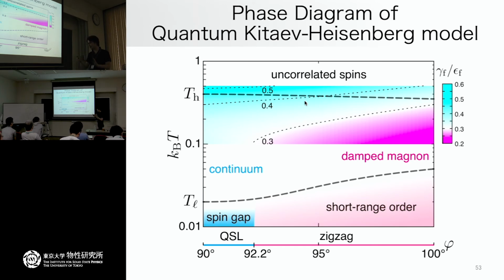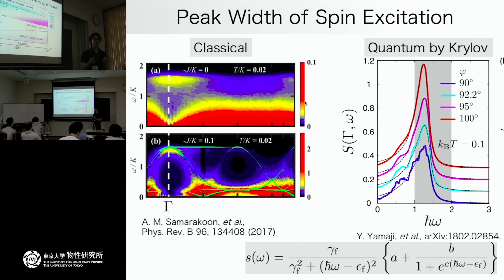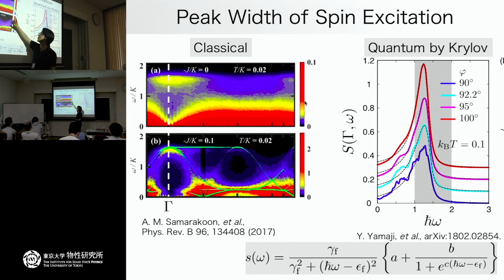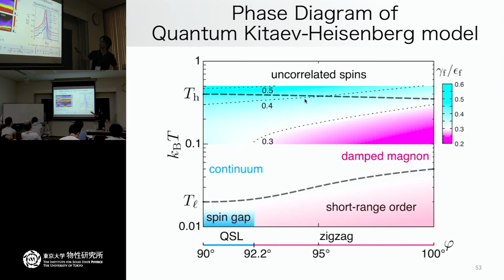But let me be really careful, because the temperature scale in the quantum limit and the classical limit is a bit different. So we should pin down which specific temperature scale to compare in the quantum cases and the classical cases. And unfortunately, near the Kitaev spin liquid case, the temperature scale in the quantum and the classical is quite different. So frankly speaking, we should be careful about the comparison, because here I just compare with, for example, this data from Christian's group, which is observed more or less around the ground state. It's really low temperature. And even at this low temperature scale, there is some finite width here and finite width here, and then we just compare with this. So in this sense, we should be careful.